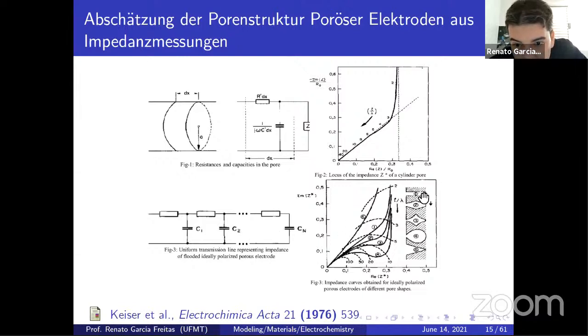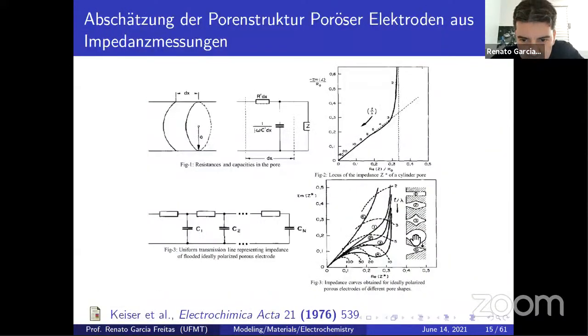So if you take a look here, a very common one, cylindrical pores, we observe like this one, 45 degrees and it goes up. This morphology, like a lozenge, when we start to decrease the charge transfer part here. The morphology of pore 3, like this one, a bubble, with a very small mouth. Pore 4, let's consider here, and an open one, number 5, is quite similar to number 1. If you take a look at the impedance profile, 5 is pretty similar to 1. So Keiser was the first to pay attention to this middle impedance and the morphology of the pores.